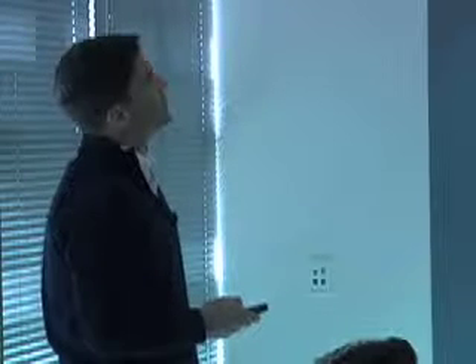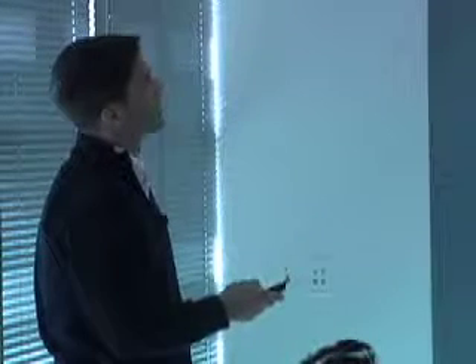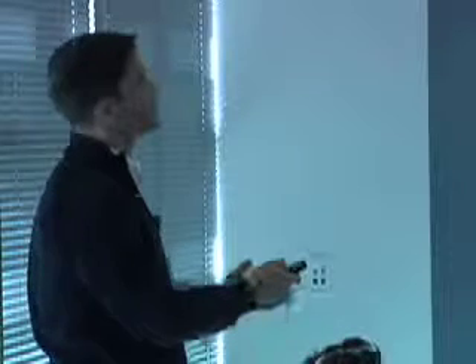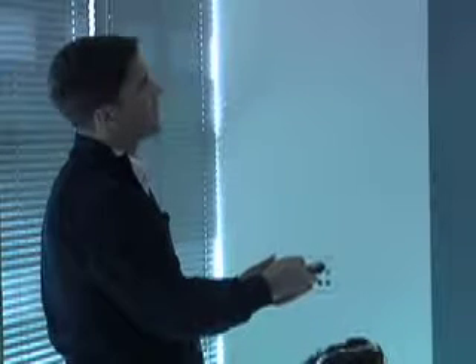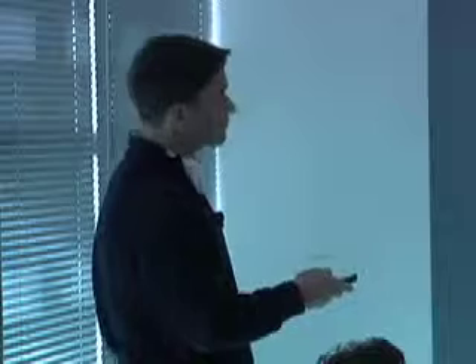This is looking at the module cost. You can make some assumptions about module efficiency of 10%, active layer thickness of 200 nanometers, and volume fraction of the acceptor of 50%. You can see that in the end, the cost associated with the fullerene is significant, and it really cannot be ignored. So I'm building this up to where we enter this equation.